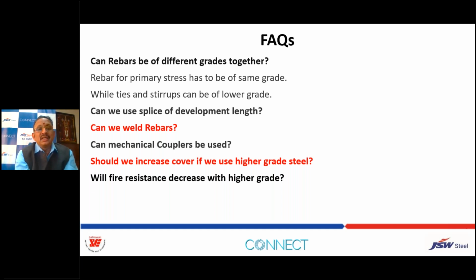And should we increase the cover if we use higher grade steel? So as I explained, cover is not dependent on the grade of the steel. Cover is mainly for the exposure conditions and durability criteria. So maintain the cover as per the durability criteria. Will fire resistance decrease with higher grade? No. That's what I said. Fire resistance is governed by the composition, chemical properties of the rebar. So check the phosphorus and sulfur content in the rebar.